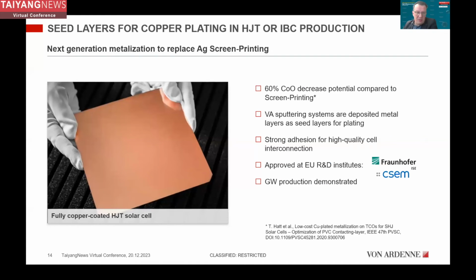So at the end, I want to also show you the approach where you can start with a copper coating, or let's say it's a layer stack, but it finishes with a copper, which you can use as a seed layer for the plating approaches. For sure, you have to think about the structuring and so on and so forth, but there are solutions out there. And this process was developed already a couple of years back with different institutes here, Fraunhofer and CSEM, and is now in production on gigawatt scale. So this shows that by applying sputtering technology, you can get rid of the silver content.